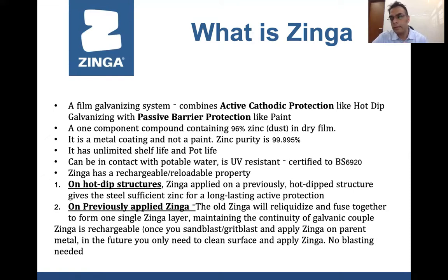Now, hot dip galvanization is a process where I'm putting zinc onto the parent metal. So Zinga complements that. After a few years, when you see that the hot dip layer is starting to get corroded, you need to just clean the surface and then apply Zinga, and it will form a homogeneous layer with the zinc in the hot dip galvanized layer. So as a result, it is rechargeable. Suppose I have applied Zinga today, or suppose I've done hot dip today. After 30 years, when I apply it again, it will again form a homogeneous layer. Each year, the thickness keeps reducing because it is a process where the zinc is sacrificing itself to the atmosphere.